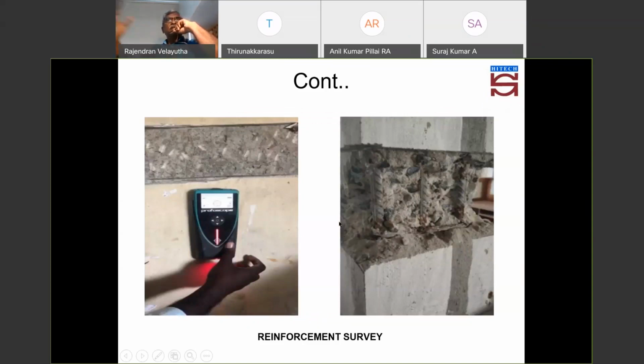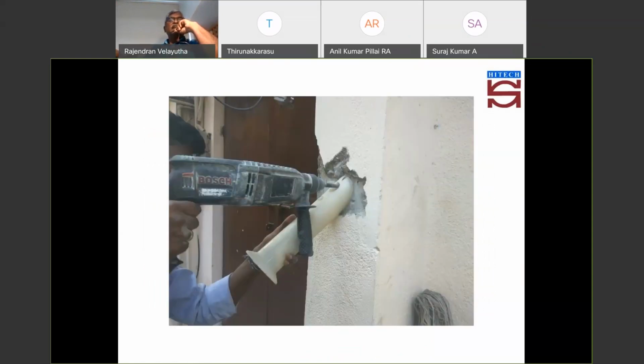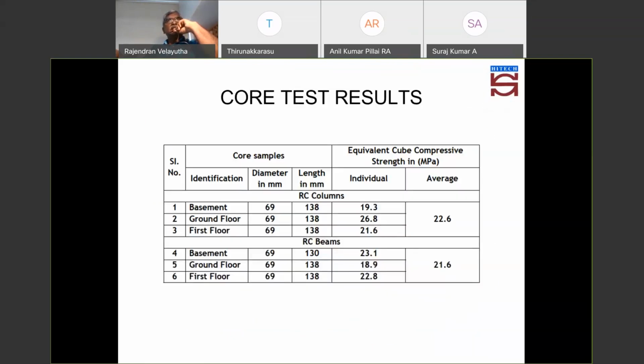Otherwise, as they say, a 20% variation gives a huge difference in the percentage of steel, and then we get into misleading inferences. Of course, as it is a 30-year-old building, we also did a few tests for ultrasonic pulse velocity, and collection of powder samples for testing chloride concentration.